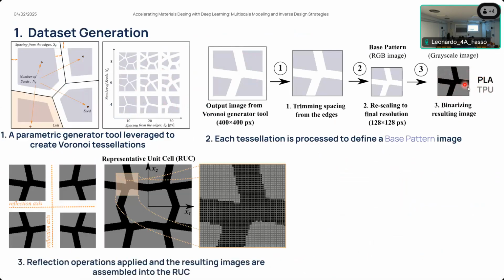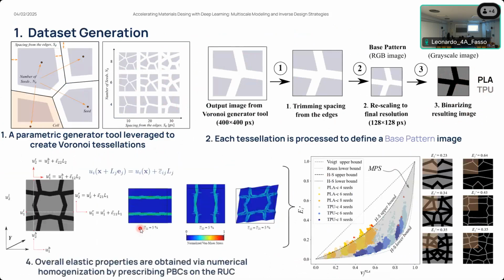Next, we use the base pattern. We perform some reflection operations, and we use the resulting 4 images. We assemble them together to obtain the representative unit cell, which is essentially the unit cell characterizing the composite materials with the periodic microstructure. Once we have the images of the microstructure, we also perform numerical homogenization in order to obtain the target values associated to this data set of images. So we now have the 2 pieces of information that we need, both the structure and also the target values.